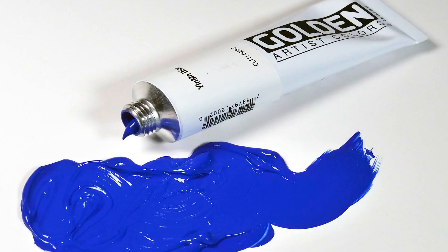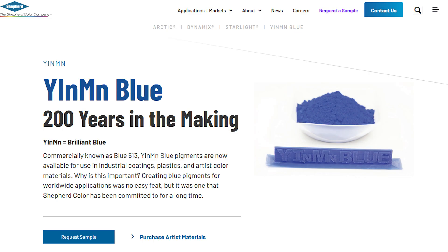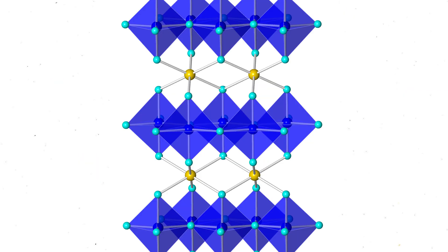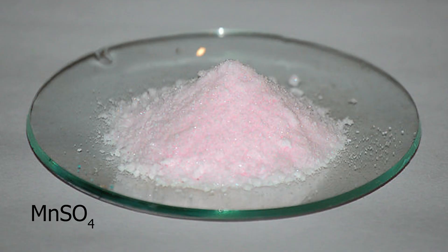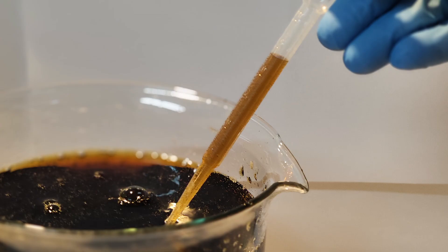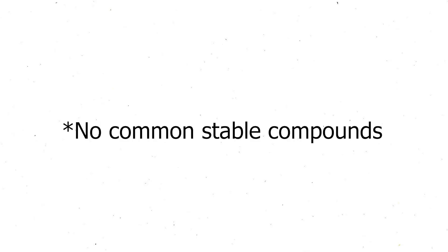Today the pigment is sold by Golden Paints, which sources the pigment from the Shepherd Color Company. YInMn blue's color arises from trivalent manganese ions, which are bound in a trigonal bipyramidal crystal structure. This is quite unique, since the usual color of trivalent manganese is red. Other typical colors of manganese include pink when the oxidation state is +2, +4 is brown, +5 is blue, +6 is green.